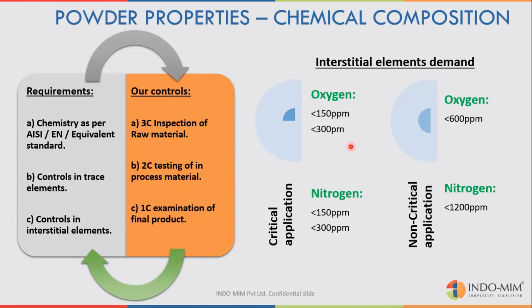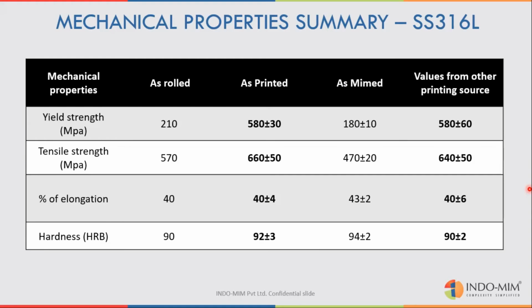So what I'm referring to here is the gaseous content, primarily the oxygen and nitrogen content. An interesting fact is that the yield strength of the material is almost 3 times higher than the conventional process. Even the as-rolled process is believed to give better mechanical properties, but additive manufacturing gives values much better than the conventional process, interestingly, without dropping the percentage of elongation.